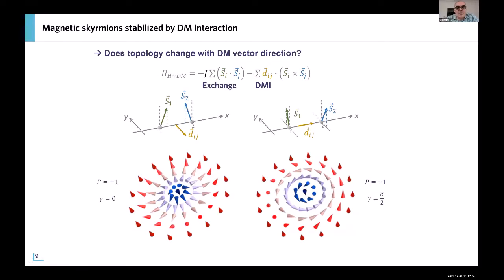Just one word about, I think this is important, that topology and chirality are two different quantities and characteristics, because you can have different chirality or different direction of the Dzyaloshinskii-Moriya vector. You see here again, for the interfacial Dzyaloshinskii-Moriya case, you can stabilize what are called Néel skyrmions or hedgehog skyrmions. And if you have a bulk break of inversion symmetry, you will stabilize Bloch skyrmions or vortex skyrmions. So you see they are different in terms of the way the whirling is occurring, but the topology is the same. In both cases, we have the topology equal to -1.